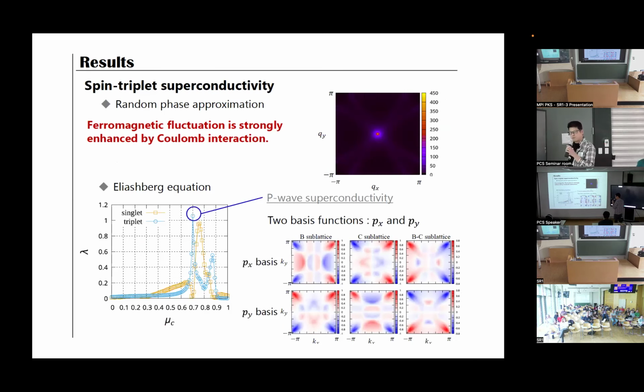So finally, we studied the superconductivity in this model. When we take into account the Coulomb interactions, by using the random phase approximation, the ferromagnetic spin fluctuation is significantly enhanced like this. And by using these spin fluctuations, we evaluated the superconducting instabilities by solving the Eliashberg equations. So here, I am showing the chemical potential dependence of the eigenvalue of the Eliashberg equations.